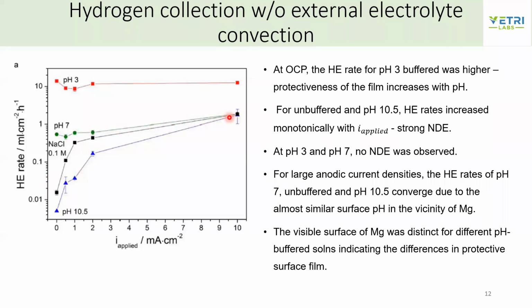However, when large anodic current densities were applied, they were able to see that the surface pH in the vicinity of magnesium tended to be almost similar. For this reason, they stated that the hydrogen evolution was almost the same in pH7 unbuffered and pH 10.5.